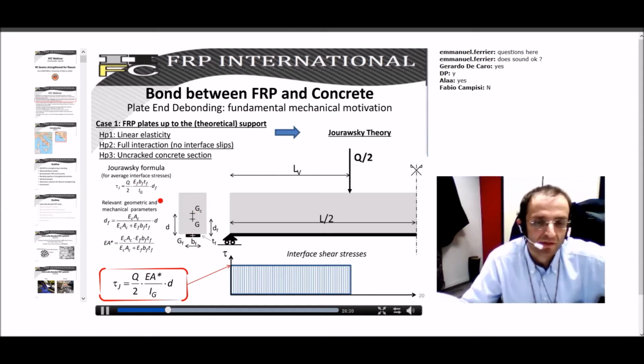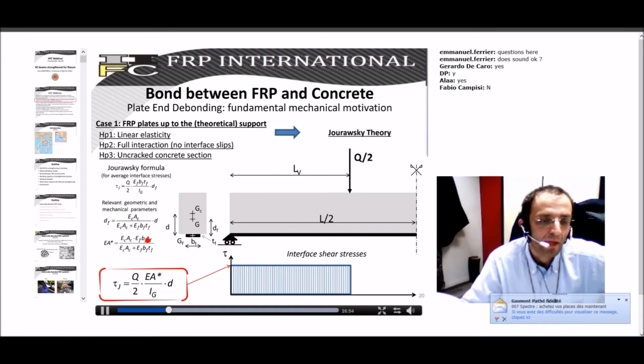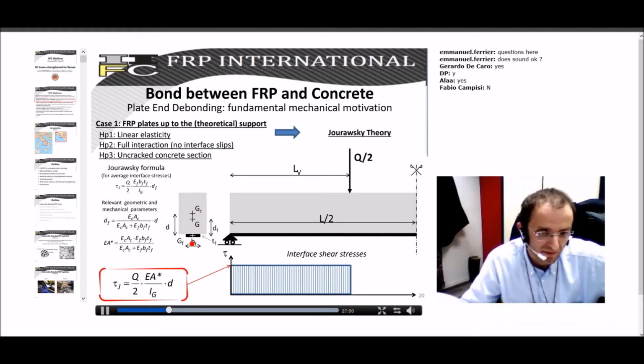So what is important is that if you work out this relationship, you can easily realize that Tj can be expressed by means of this EA star, which is an equivalent axial stiffness of the members, taking into account both the axial stiffness of the RC beam and the axial stiffness of the FRP, and also D, which is the theoretical distance between the centroid of the strip and the centroid of the RC beam.